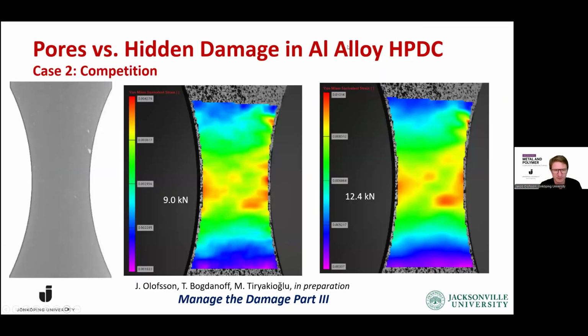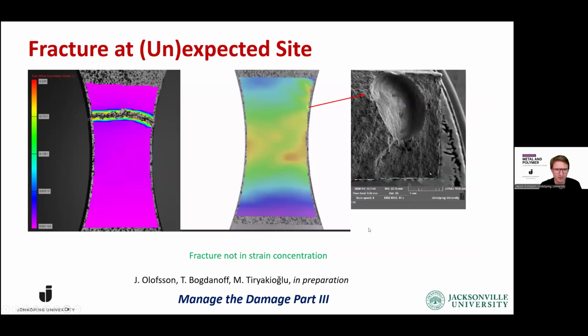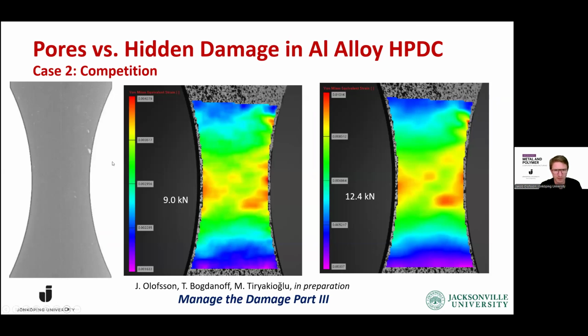The next case, you can see again that there is a competition between different defects here. So you see in the X-ray picture on the right side there that there is a clear big porosity, but there are also other effects that are going on when we look at the strain field. We can see on the left side there's a bit of this geometrical thing that we would expect, but on the right there is clearly something else happening here. And as we increase the load there, that seems to be the winner. That's in the central area here, that there's clearly something causing a high strain here.